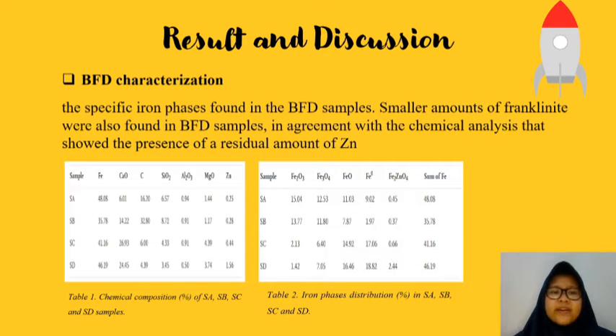First is BFD characterization. The specific iron phases found in BFD samples. Smaller amounts of franklinite were also found in BFD samples, in agreement with the chemical analysis that showed the presence of residual amounts of Zn. We can see in table number 1 the chemical composition of samples SA, SB, SC, and SD. And table number 2 is the iron phases distribution in SA, SB, SC, and SD. We can see in table number 2 the smaller amount of franklinite.